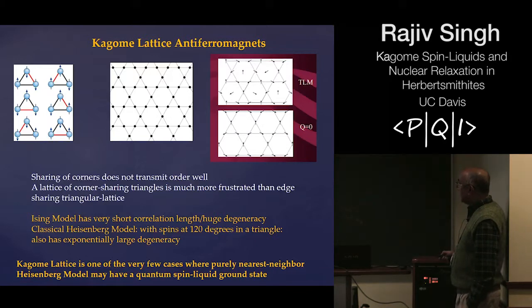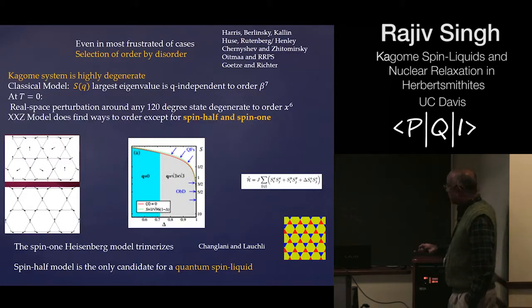But if you consider a classical Heisenberg model on the Kagome lattice, because it's a lattice of corner sharing triangles, the order doesn't propagate from one triangle to the next, and in fact one can show that one still retains an exponentially large number of possible configurations that remain exactly degenerate. After a lot of numerical studies, the Kagome lattice is one of the very few cases where a purely nearest neighbor Heisenberg model may have a quantum spin liquid ground state without adding any extra perturbation to the system, really. Okay, so there have been a lot of studies of the Kagome lattice.